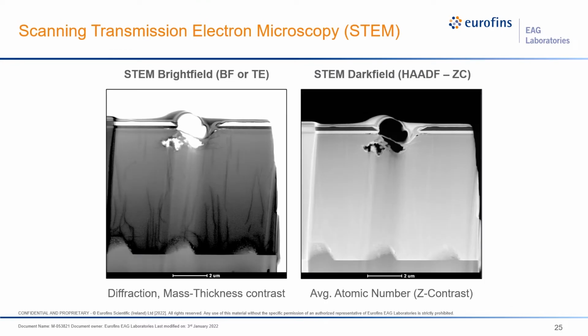This is an example now of looking through a thin section that we've removed. We've thinned this lift-out cross section. It's probably 150 nanometers thick or so. And so this gives us now an idea of what's going on within the crystal itself. In the bright field mode, we can really see the evolution of a lot of threading dislocations up through the epitaxy.